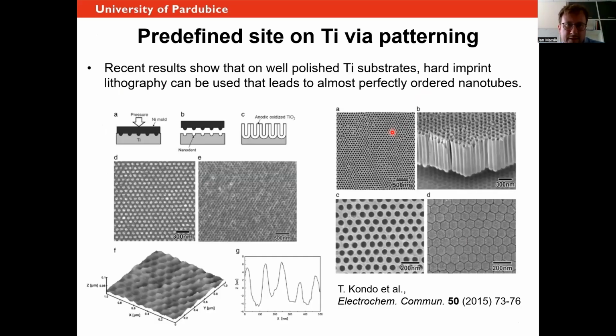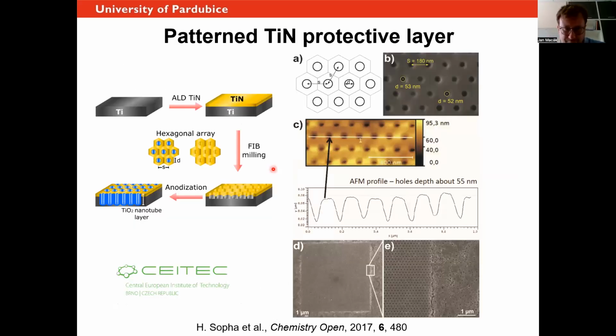So recently, like years ago, there were some efforts how to, for instance, do some imprinting in the titanium using nano indentation or ion-pit lithography. So you can actually take a mold with a certain distance, you can imprint some holes in the titanium, and then you can anodize for a short time. But you can see that still the surface is not very perfect at the surface. It looks good at the bottom, but not yet at the surface.